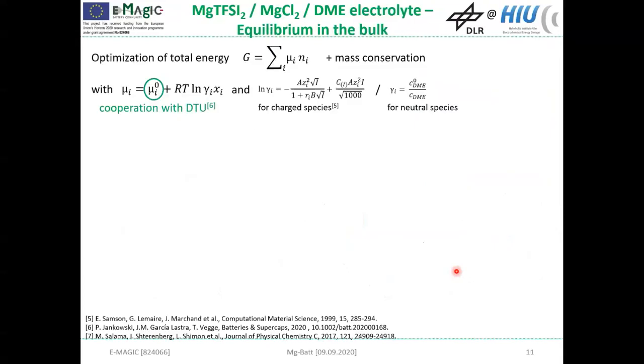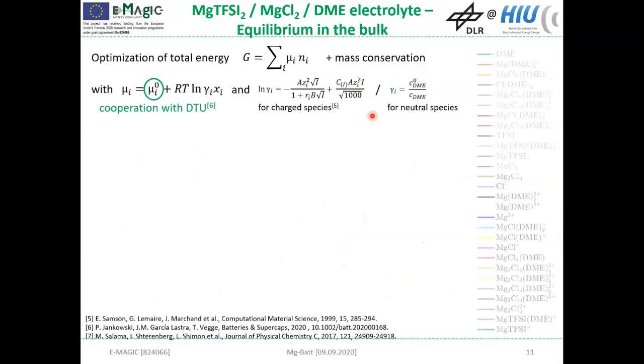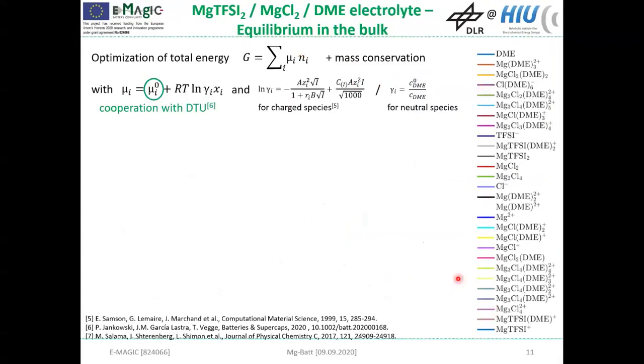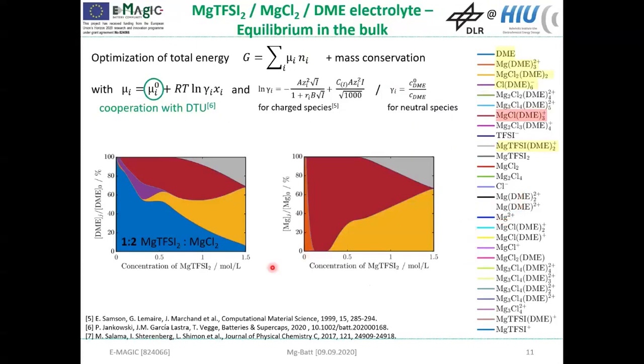So what we do is we minimize the total energy of the system, and thereby we apply mass conservation as a constraint. And we also consider the non-ideality effect. As you can see here, we included lots of different magnesium chloride species in our calculation. For example, we also considered partially solvated and unsolvated species because at non-dilute concentrations, they could become favorable due to entropy effects. Usually our partners use MgTFSI2 to MgCl2 in a ratio of 1:2. That's the reason why we had a look at this electrolyte composition.